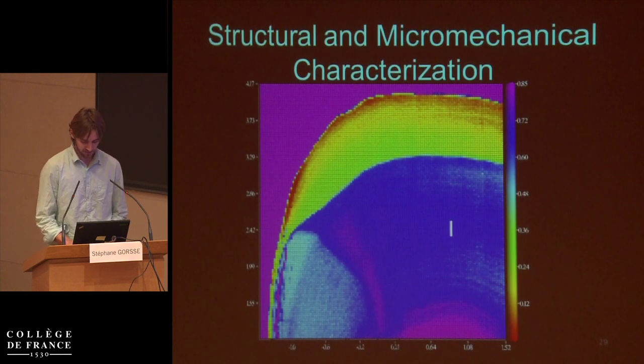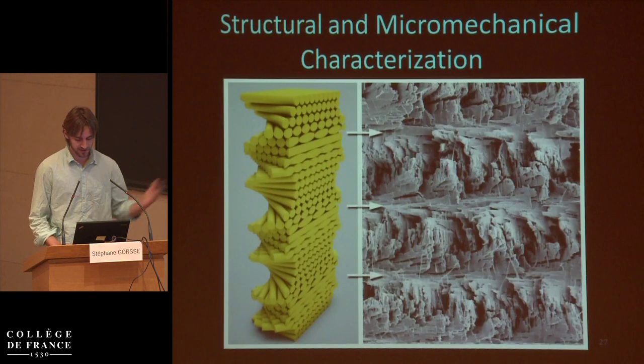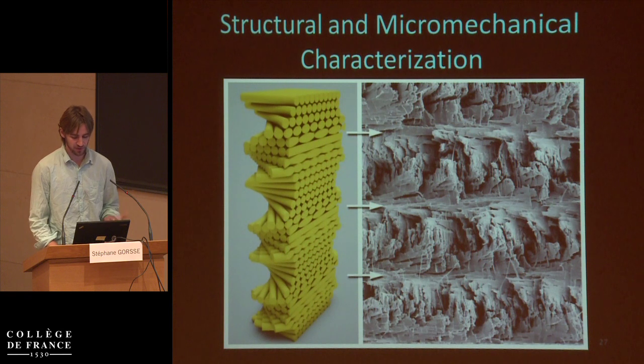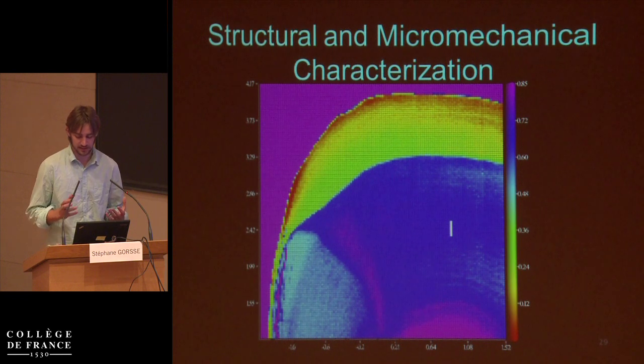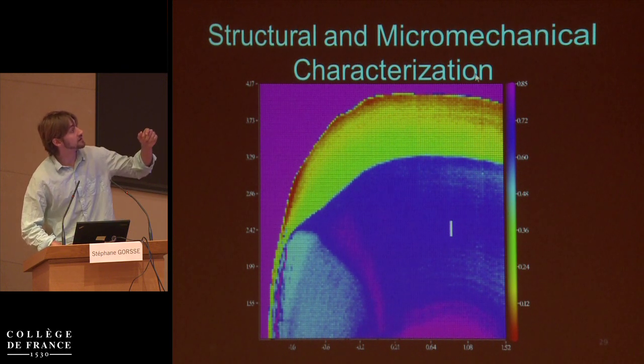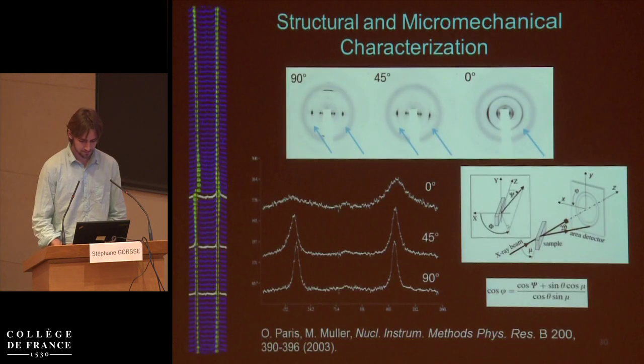So one of the first things we wanted to do was, in looking at this fracture surface, it's very difficult to determine where the fibers begin and the matrix ends. And so with synchrotron, because the mineral phase is amorphous, it was very easy to distinguish between the mineral phase and the crystalline chitin. So taking a line scan along that white bar down the central axis of the club, right here being the impact surface, we could take all these traces around the 110 reflection of chitin and stack them on top of each other.